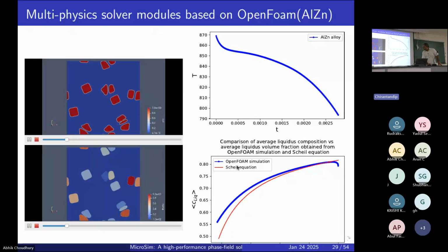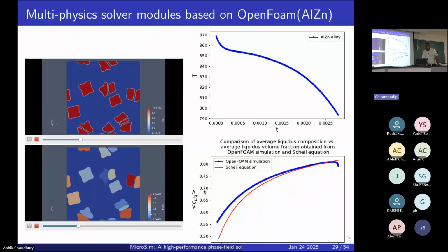These phase-field simulations are then compared with the Scheil. It's not like Scheil is correct and we are coming close to it. That's not true. Scheil is restrictive in its assumptions. The reality is closer to what the simulations are showing. Scheil is only one extreme edge, rather than the lever rule assumption, so it's only telling you one limiting case for you to see whether the simulations are the same.